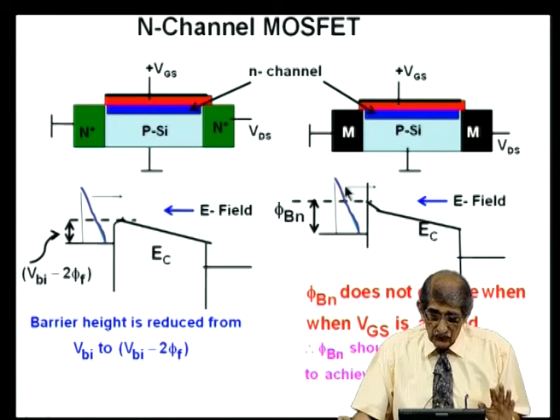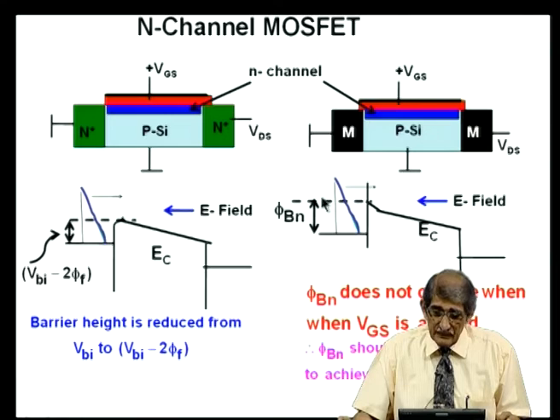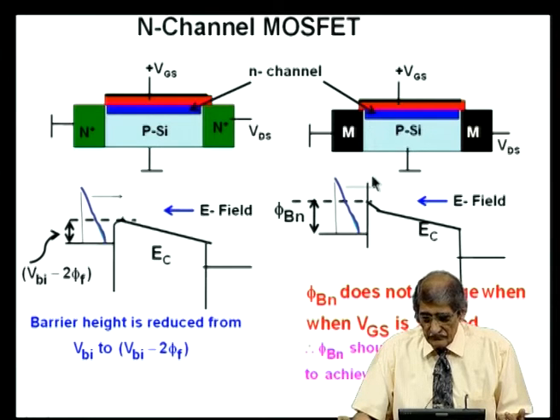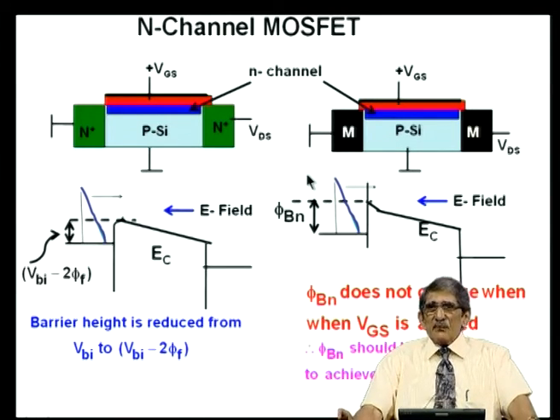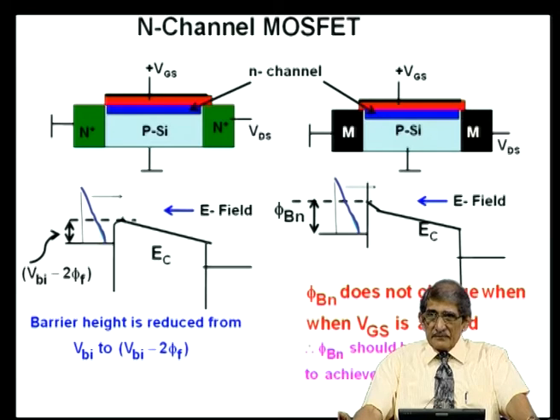That is the difference. So, what we see is if you want to have a large supply of electrons here, phi b n should be small. Barrier height should be small. That means ideally it should make an ohmic contact onto this channel. Of course, the electrons which are injected here can roll down because of the voltage drop in the channel and will be collected. The current will be limited by the supply available here. So, you need to reduce the barrier height, phi b n. What one immediately thinks of is phi m minus chi. An n type material will give you a high barrier height if phi m is greater than chi. But if phi m is small, then it will ideally give an ohmic contact.